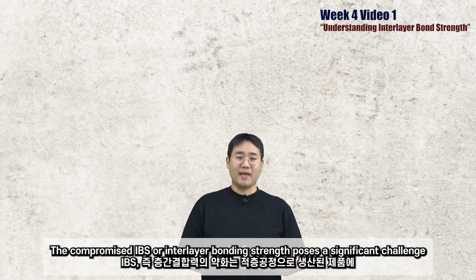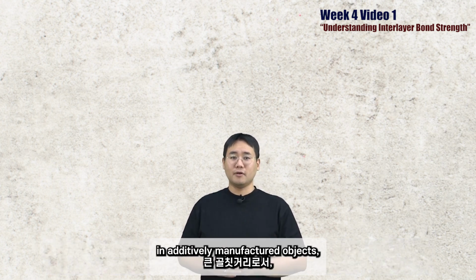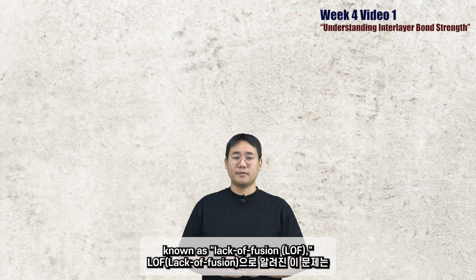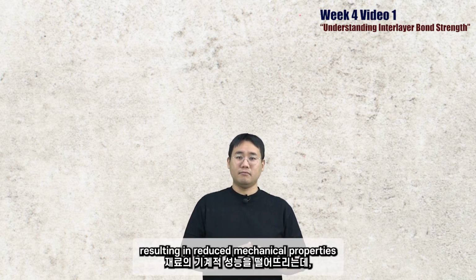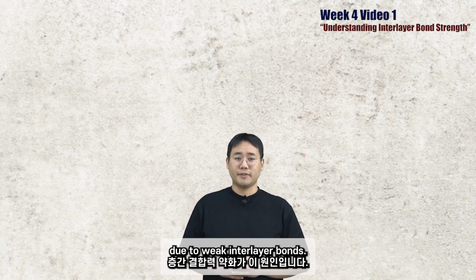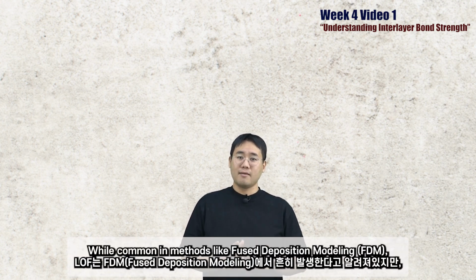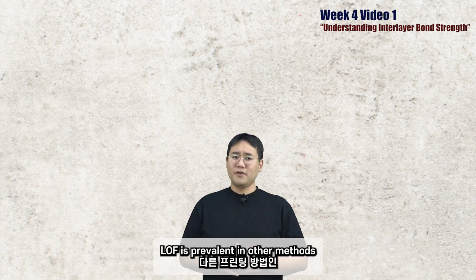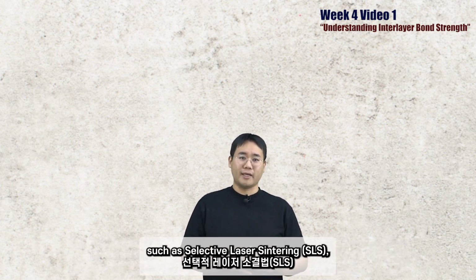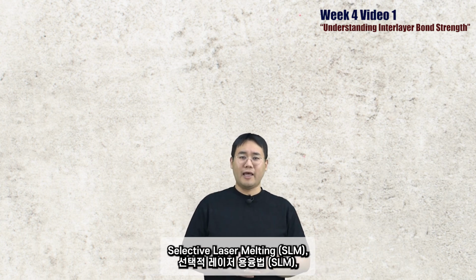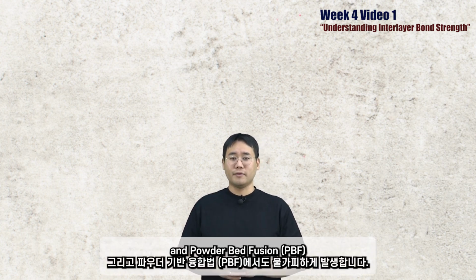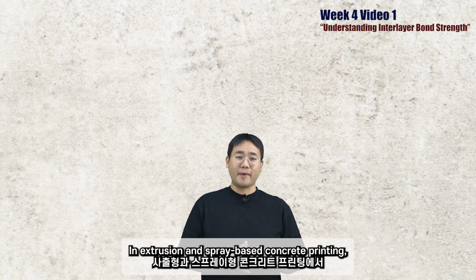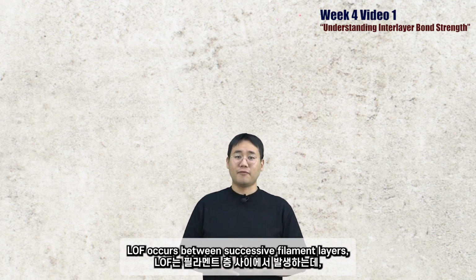The compromised IBS, or interlayer bonding strength, poses a significant challenge in additive manufactured objects, known as lack of fusion, resulting in reduced mechanical properties due to weak interlayer bonds. While that is common in methods like fused deposition modeling, FDM, lack of fusion is prevalent in other methods such as selective laser sintering, selective laser melting, and powder bed fusion. In extrusion and spray-based concrete printing, lack of fusion occurs between successive filament layers.